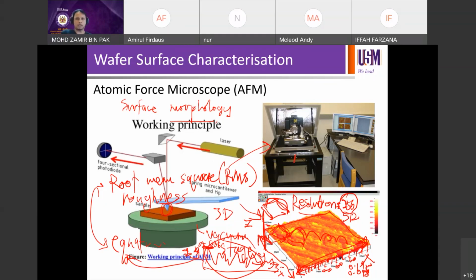From here you can see if your sample is very flat, for example, if you scan a bare glass substrate or a bare silicon substrate, where you haven't done anything yet on the wafer or on the glass, and you just scan the AFM, then you'll see a very smooth surface with RMS typically below 3 nanometer. If it's very flat, maybe about 3 nanometer or so, or lesser than that, 1 or 2. That shows a very flat, very smooth surface.